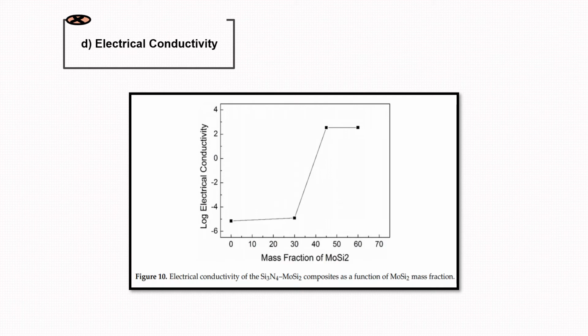When the molybdenum disilicide content increased above the percolation threshold, the percolation network of molybdenum disilicide formed, and as a result, the electrical conductivity was mainly contributed by the molybdenum disilicide phase rather than the matrix, thus showing high electrical conductivity. In this study, it can be claimed that the percolation threshold is located between 30 weight percentage to 45 weight percentage.